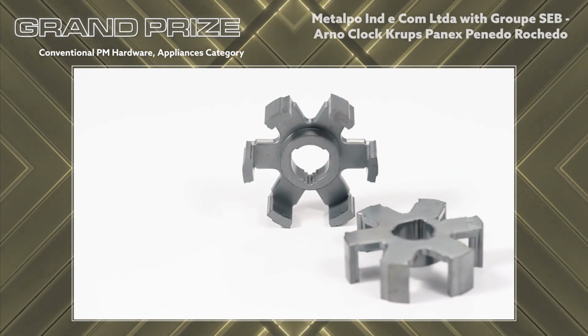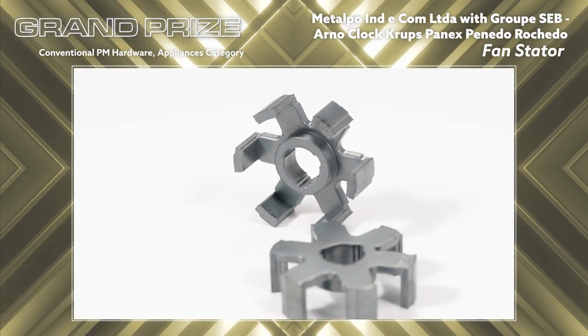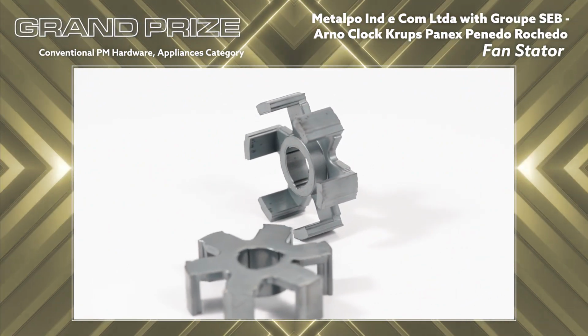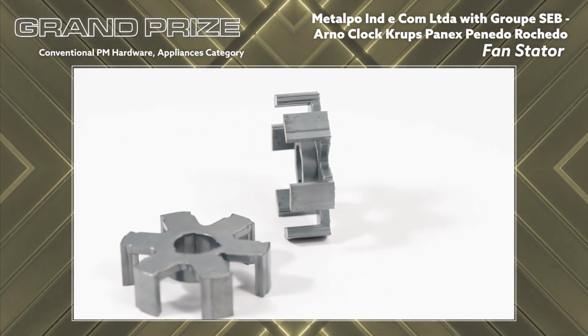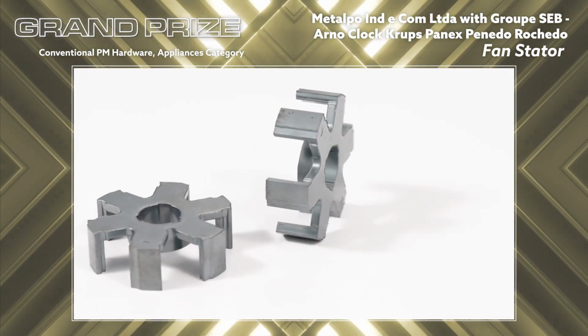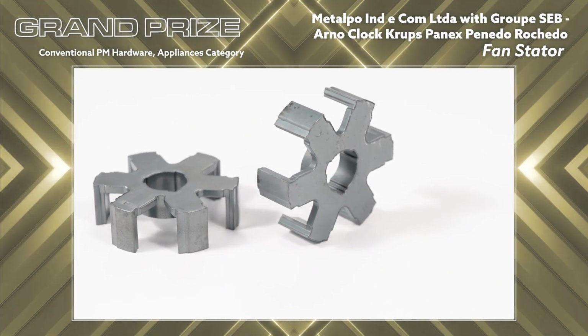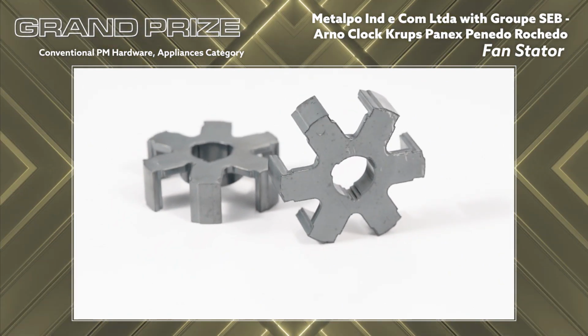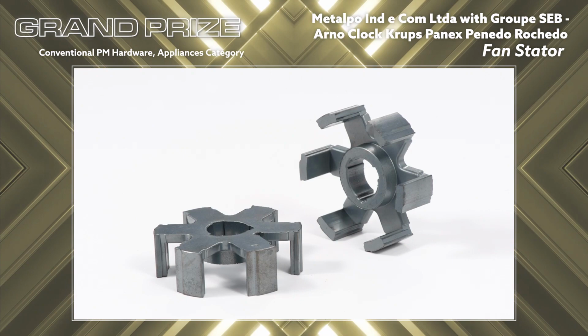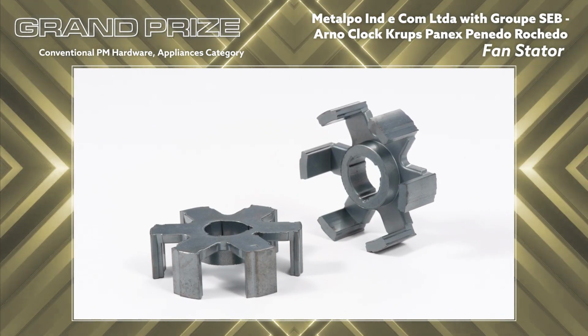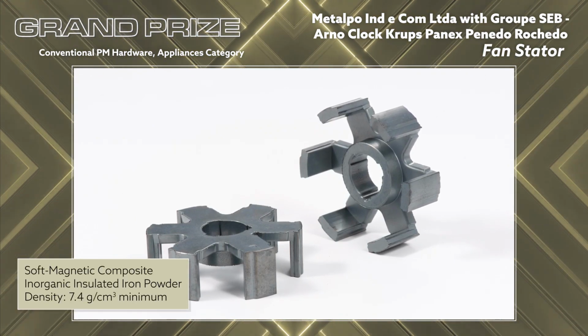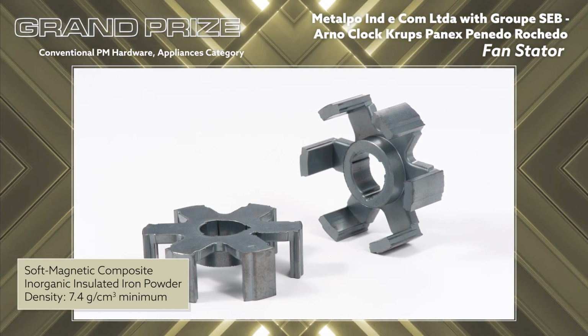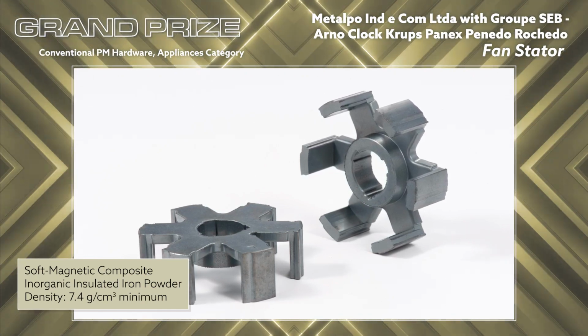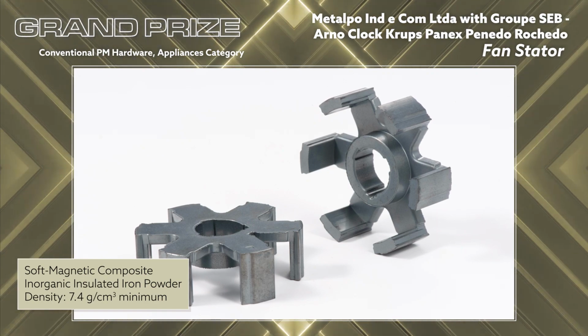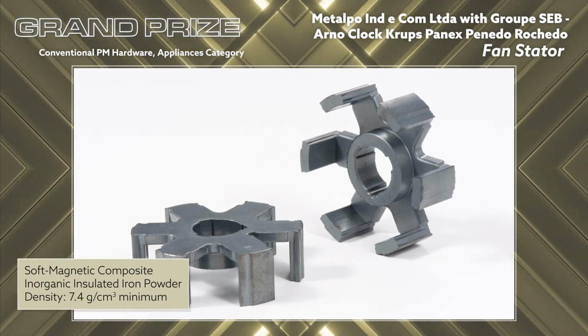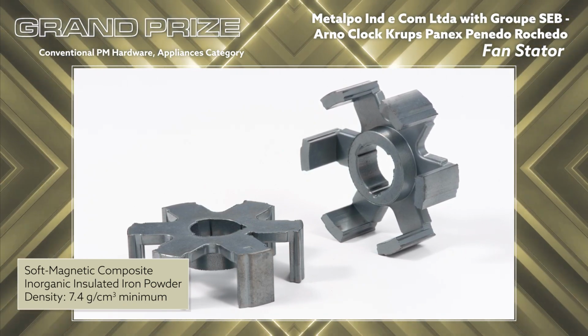In the hardware appliances category for conventional PM components, a grand prize has been awarded to Metalpo Ind e Com Ltda and their customer Group Seb Arno Clock Krups Panex Penedo Rochedo for a soft magnetic composite superior and inferior stator for a monophase induction motor for a ceiling fan. The parts are made using an iron powder coated with an insulating inorganic material that has high resistivity, and the parts have excellent magnetic permeability. A high compacting pressure of 800 megapascal is needed to achieve the 7.4 grams per cubic centimeter minimum density.